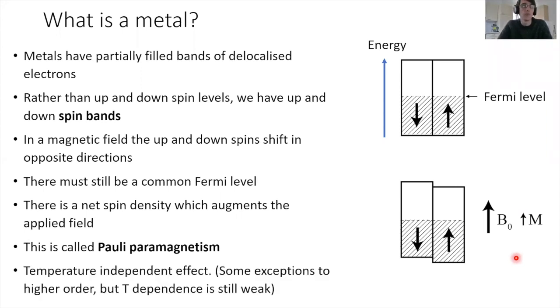And in contrast to Curie paramagnetism, this is a temperature independent effect, at least in most cases, and to at least a couple of orders of magnitude. And the reason for this is temperature can cause a smearing out of this Fermi level, so we excite some of these electrons into these states, but this happens exactly the same way in the two spin bands, and so we still end up with the same difference in population, and so we still end up with the same magnetic moment. And so the magnetic moment here is temperature independent, and that's a characteristic of Pauli paramagnetism.